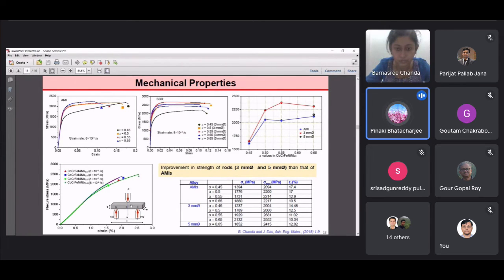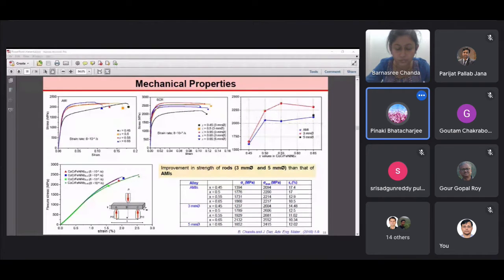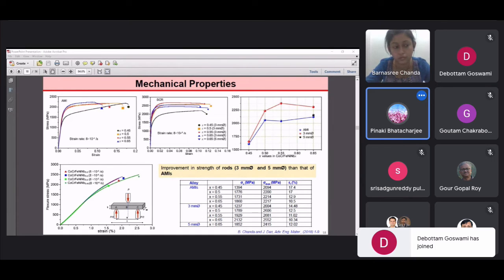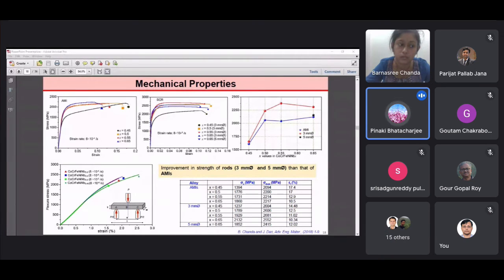Yeah. So you can basically see it has very limited ductility, and it is not uncommon to see because you have a lot of Laves phase, which is not very ductile. So that is what I wanted to say, that when we talk about eutectic high entropy alloy, this particular combination FCC plus B2 is possibly the most attractive compared to any other combination. At least this is my view, that other phase constituents do not give the kind of advantage which the aluminum, cobalt, chromium, iron, nickel 2.1 enjoys.